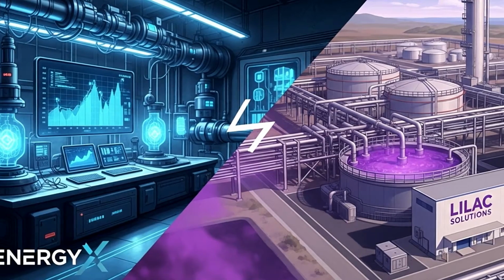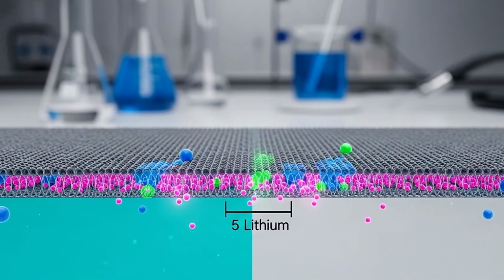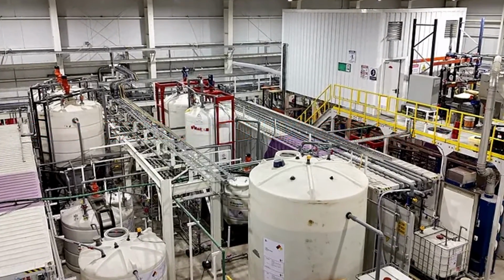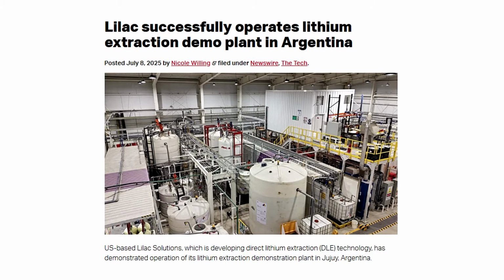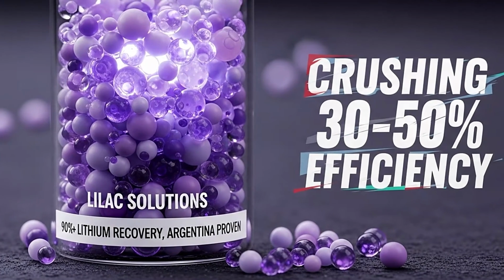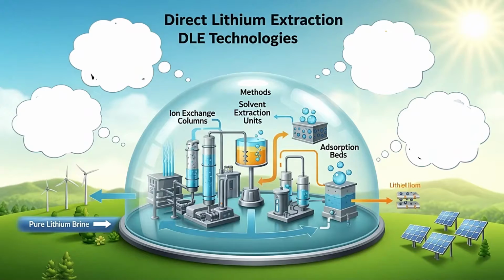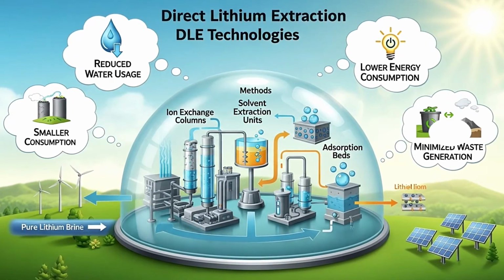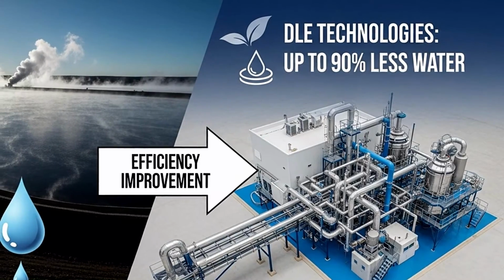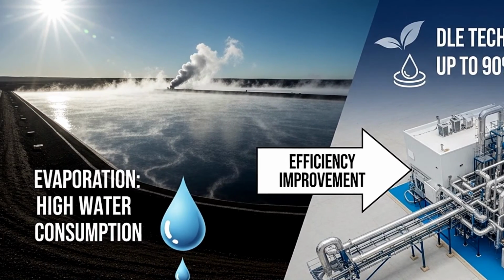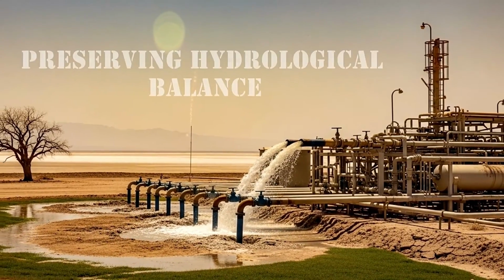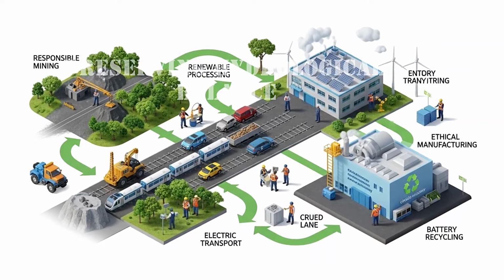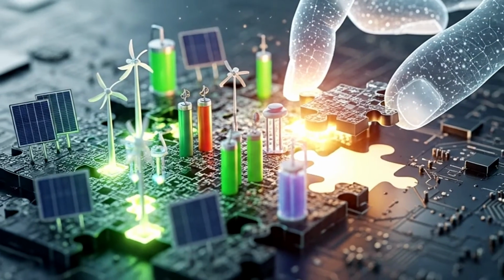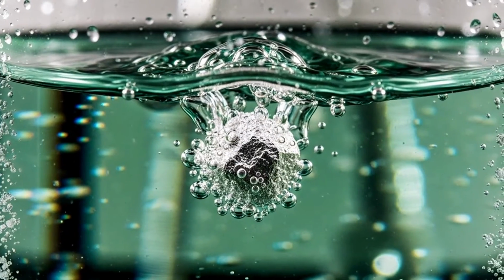Meanwhile, companies like EnergyX and Lilac Solutions are applying highly selective membranes and ion exchange technology to traditional brines in the lithium triangle. Lilac's proprietary ion exchange beads, proven in Argentina, achieve over 90% recovery, crushing the 30 to 50% efficiency of traditional methods. All these DLE technologies promise a drastically reduced environmental footprint, up to 90% less water consumption compared to evaporation. By recycling or re-injecting the processed brine, they preserve the hydrological balance, making the entire lithium supply chain far more ethical and sustainable.